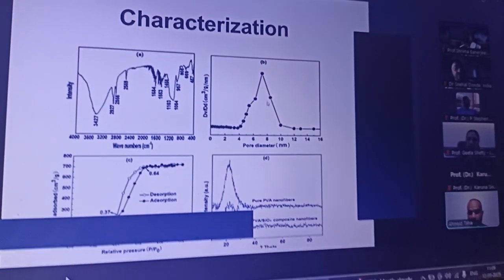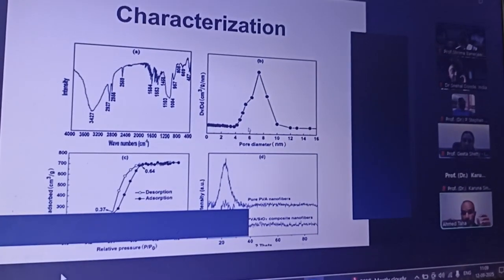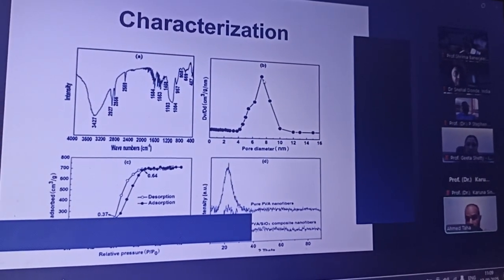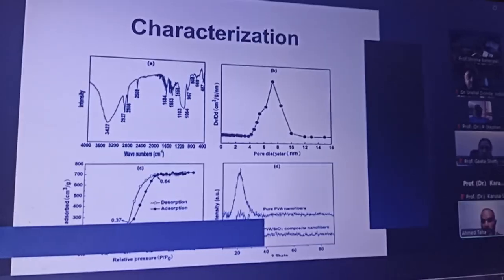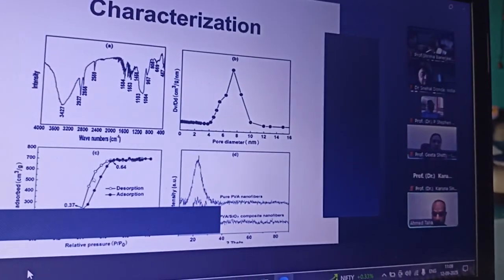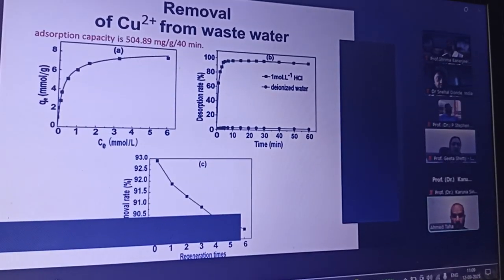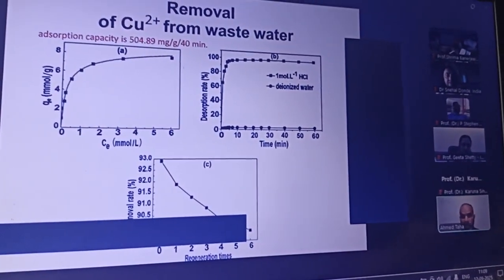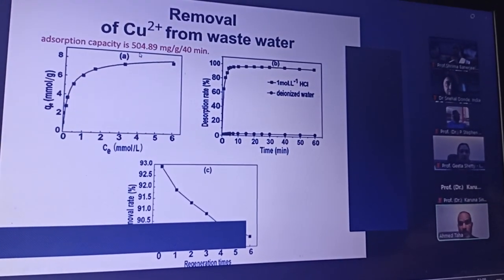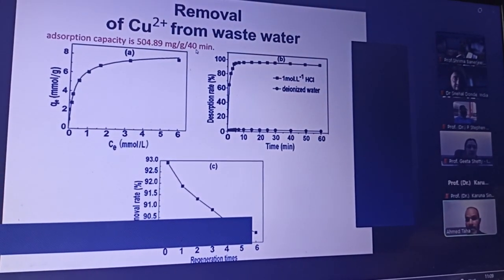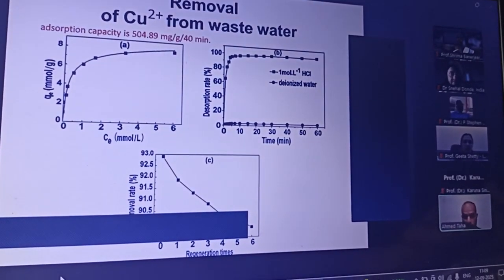These are some characterizations we do to understand the material. We look at the porosity. We have pores, so how big are these pores? These pores, for example, are around 8 nanometers, which is in the mesoporous range, which is desirable for these applications, and it also has a high surface area. Then we do the application. We have water with copper, we immerse this membrane in it, and we measure before and after some time. After 40 minutes, we found that this membrane can capture about 500 milligrams per gram of this material, which is really good performance.